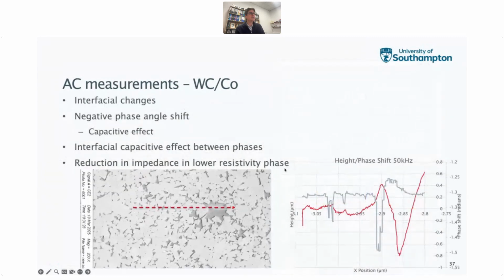And so if we do this and then try and correlate that to the surface topography, which we can also get from this technique, which is the red line here, so this has been normalized for the form error correction that we have on it, what we start to notice is that as the probe is traversing the interface between the phases, we're starting to see this negative phase angle shift, which is suggesting that it's perhaps a capacitive effect.